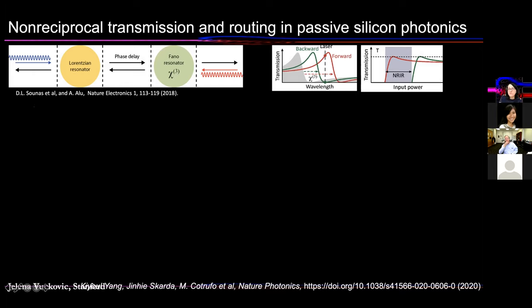So if you design the system in such a way that in the forward direction and backward direction, you couple a different amount of power to this nonlinear resonator, that means that the transmission characteristics for this resonator would shift by a different amount for forward and for backward propagating direction. So at the laser wavelength that you have, which is fixed, you will have different transmission in forward and backward direction in a certain dynamic power range.